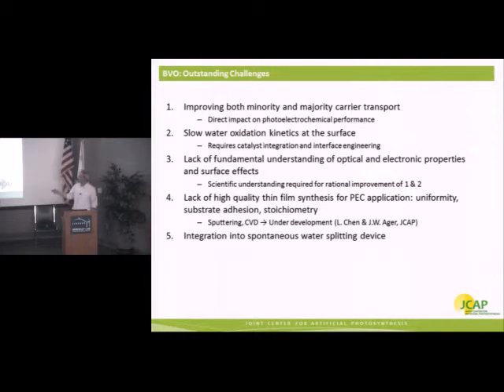And then finally, there's basically a limited range of synthesis procedures that are available for forming this material. And they're mostly based on solution phase synthesis. So the light capture group, with Le Chen and Joel Ager at JCAP, are developing means of doing physical vapor deposition of this material, which should allow improved control over stoichiometry and for integration into spontaneous water splitting device.